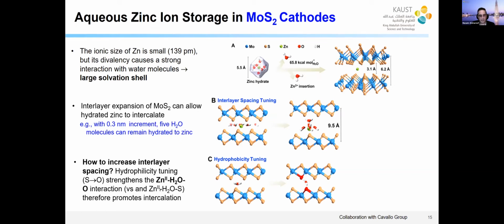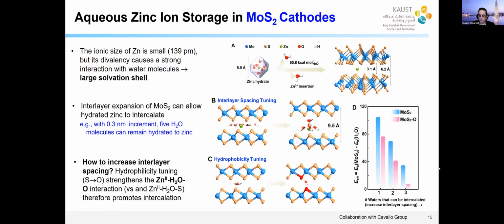Tuning the hydrophobicity of the atom. So sulfur, molysulfide is hydrophobic, but molyoxide is more hydrophilic. So you replace some of the sulfur with oxygen, and then this becomes less hydrophobic. And what this does, it allows better intercalation. So we did a calculation also to prove this.